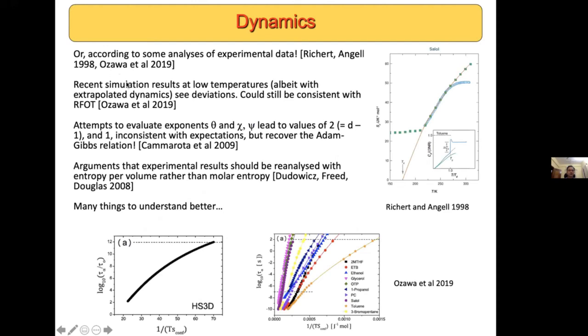okay, it's one thing to say that what you observe is not according to theoretical expectations, but it turns out it's also not according to some analyses of experimental data. And in particular, I point out here an analysis by Richert and Angell, where what this graph shows is the configurational entropy in green squares, which is actually measured through some calorimetric method. But what it is being compared with are these blue circles, which are the entropies that are estimated assuming that the Adam-Gibbs relation is valid from dynamics data. Okay, and one sees indeed that there is this regime where they actually coincide quite well. So this is an indication of the validity of the Adam-Gibbs relation.